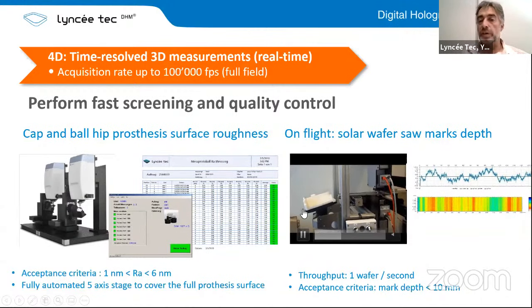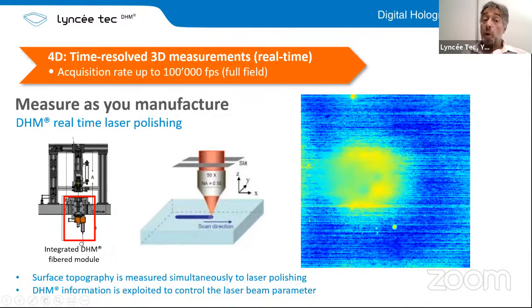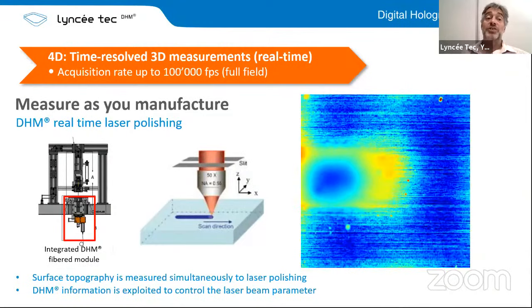The size of the wafer is 150 millimeter. The time of flight below the sensor is 0.7 seconds. In production, we have 1 wafer per second. We have 4 sensors, and we make the profile for each of them, and we make sure that there are no saw mark deeper than 10 micron. So that's very fast. It's also enabled to measure as you manufacture.